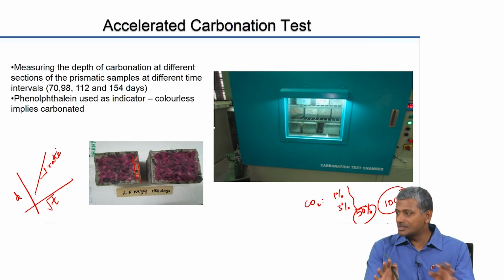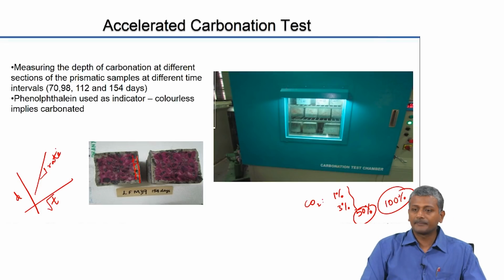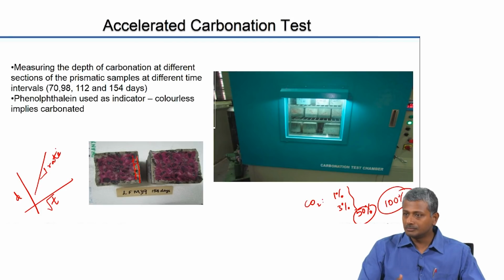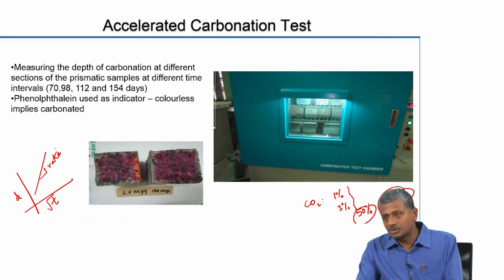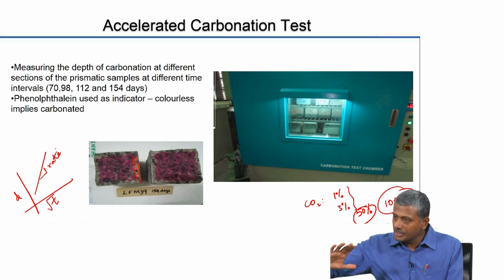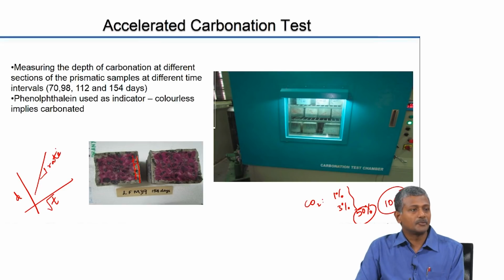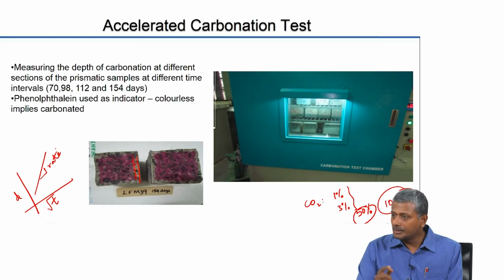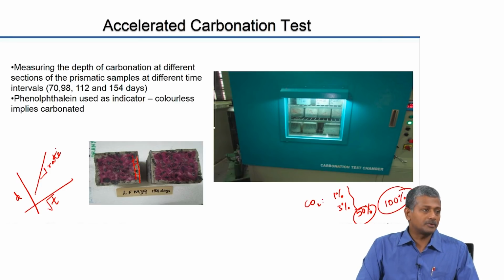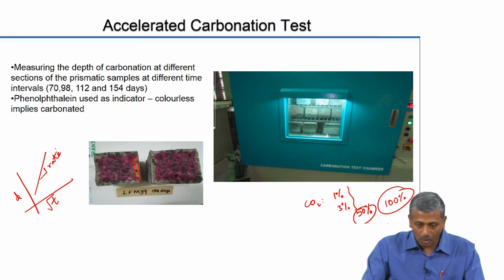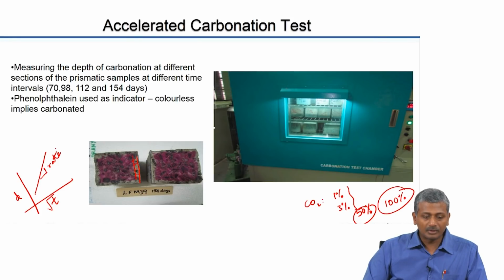On one side, you need less moisture, or partially saturated or unsaturated concrete, for the CO2 to propagate into the concrete. On the other hand, you need moisture to ensure that the corrosion propagates in a regular fashion. So, there is lack of moisture for CO2 penetration, but you need moisture for corrosion. So, although carbonation depth may be high in certain instances, you may not get the associated corrosion of the reinforcing steel, even though the pH conditions are ideally suited for corrosion to happen, because the moisture availability is a criterion that determines whether corrosion happens or not. Anyway, we will talk about that again later when we discuss corrosion in more detail.